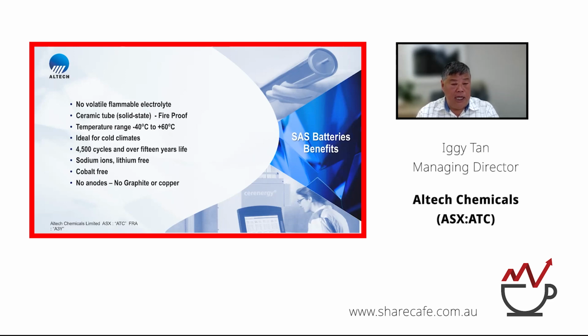Why? Because the inner temperature of the battery operates at room temperature. It's fully insulated, so you can touch the battery with your hand, but it generates its own heat and removes the heat during charge and discharge. So it is a regulation of heat. A good analogy is that it's like a mammal. A mammal can operate down at minus 40 degrees as well as up to 60 degrees. So it's ideal for cold climates.